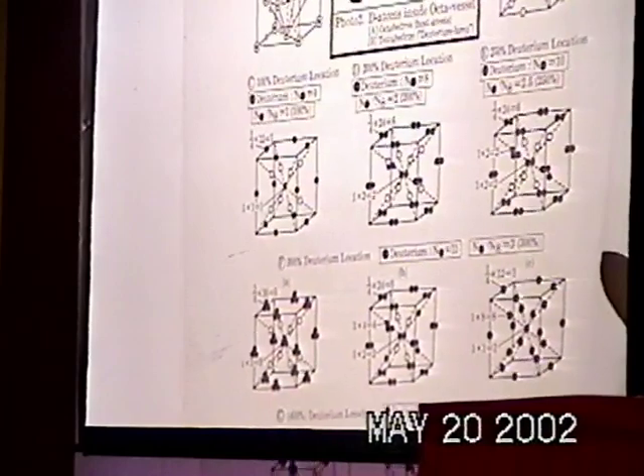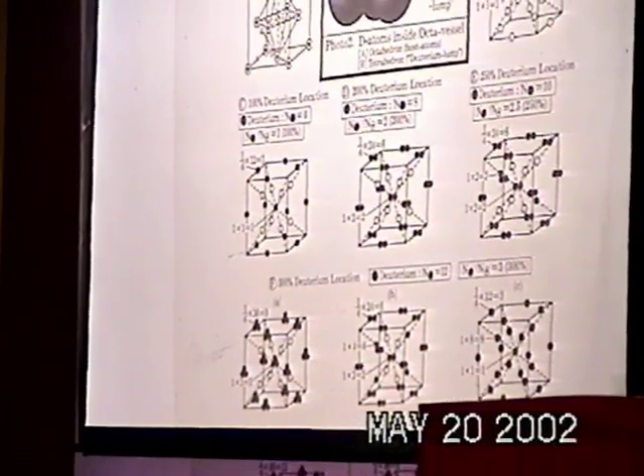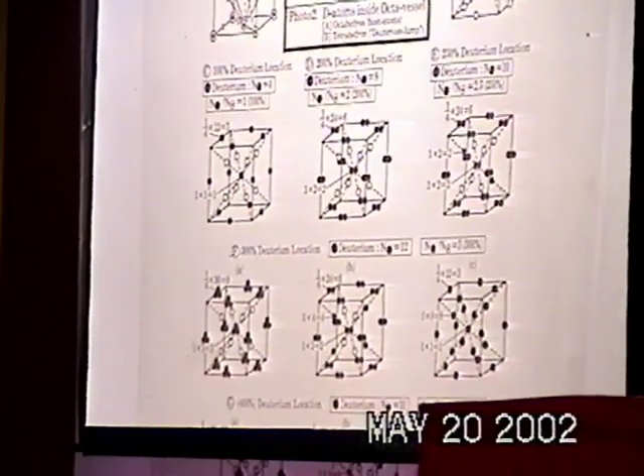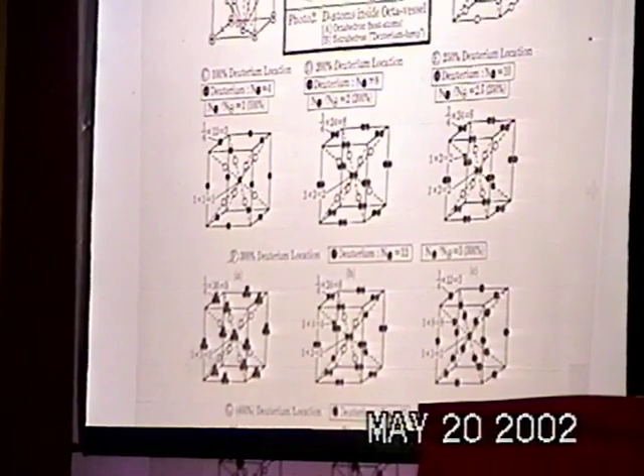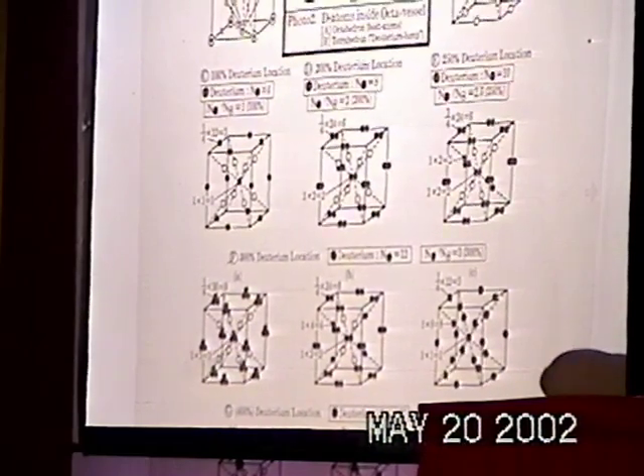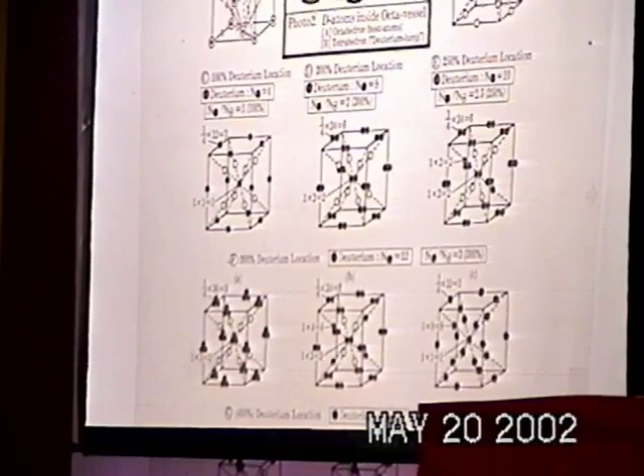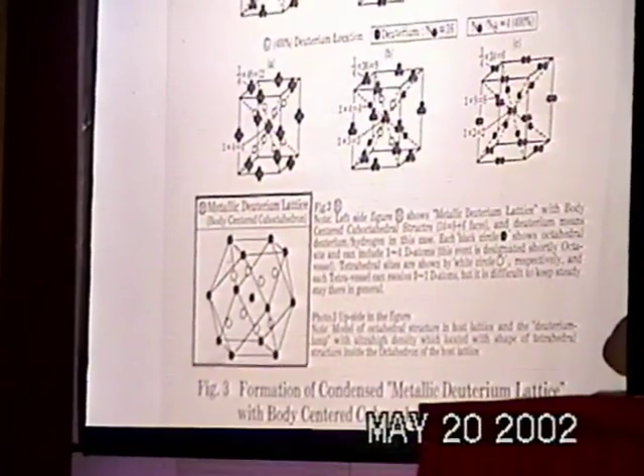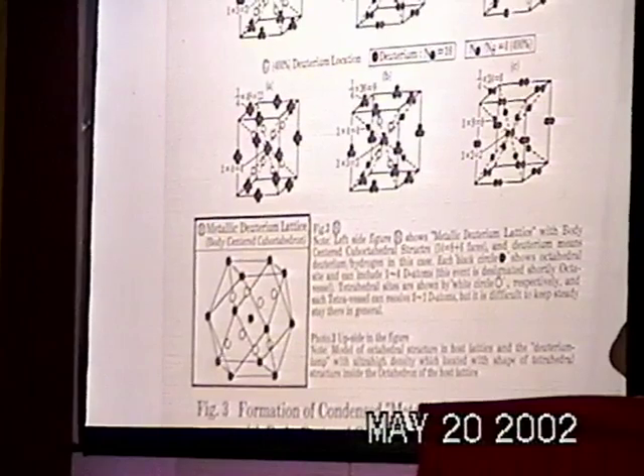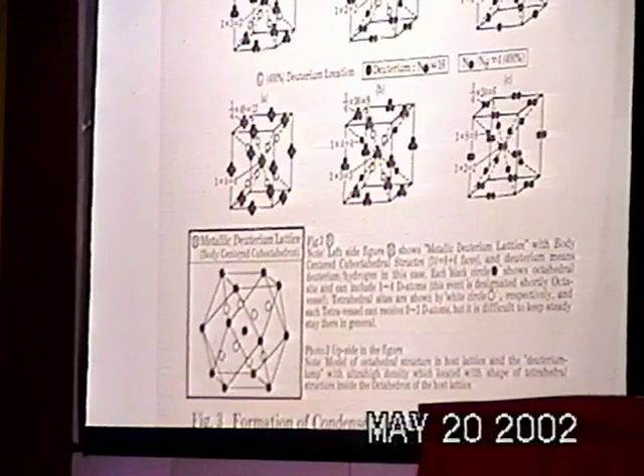This shows formation of heavily condensed metallic deuterium gas. As you see, right side top corner, diagram B. There are two kinds of gaps shown with open circles within a unit cell of FCC structure. That is octahedral and tetrahedral site. Therefore, when all sides of these gaps are occupied with D or H atoms, its atomic ratio becomes 300%, as shown right side of third line. That is small a in parentheses inside large F.